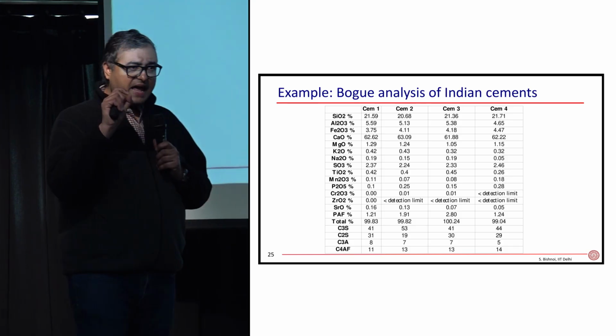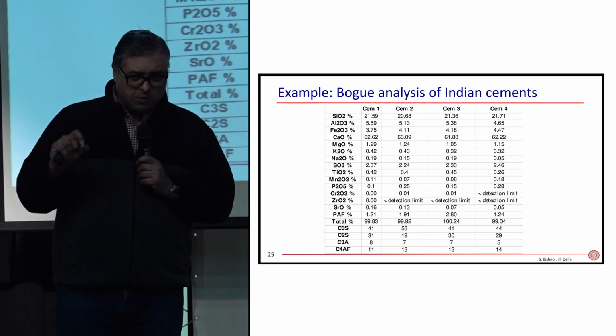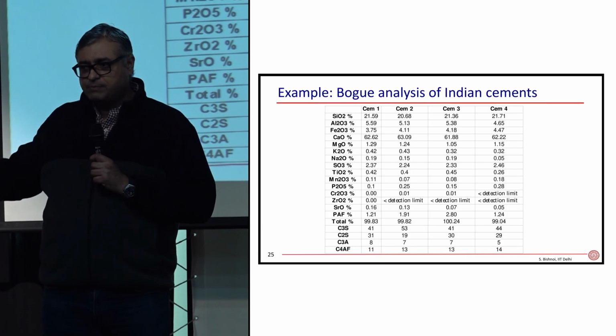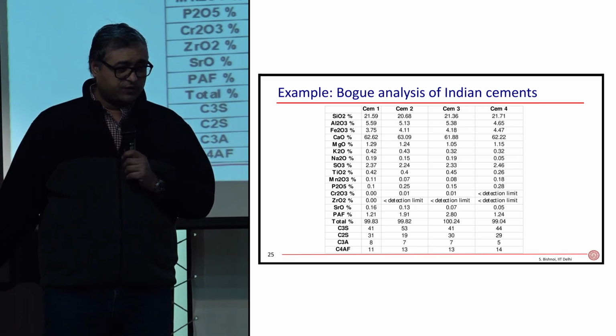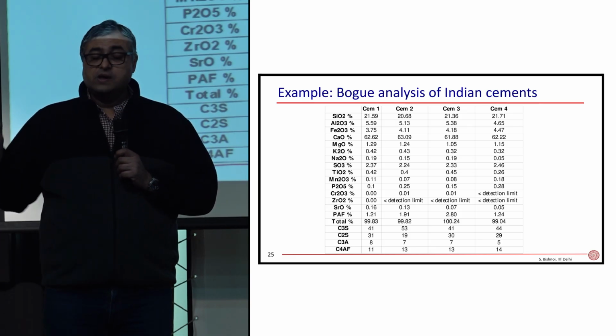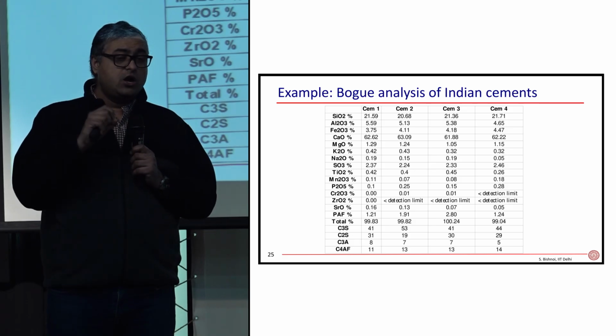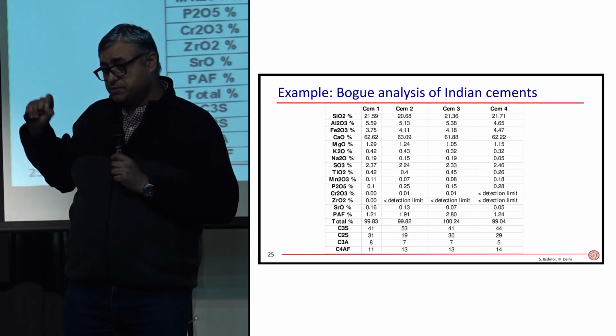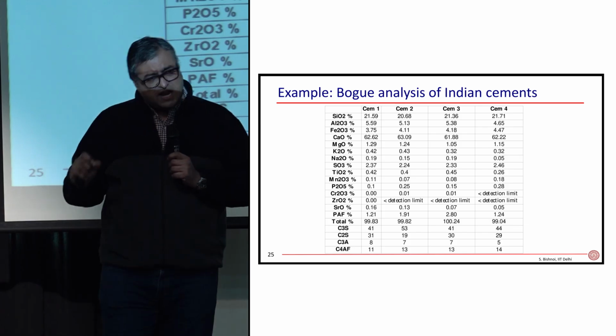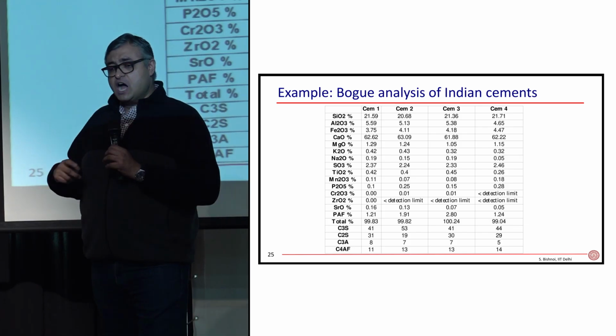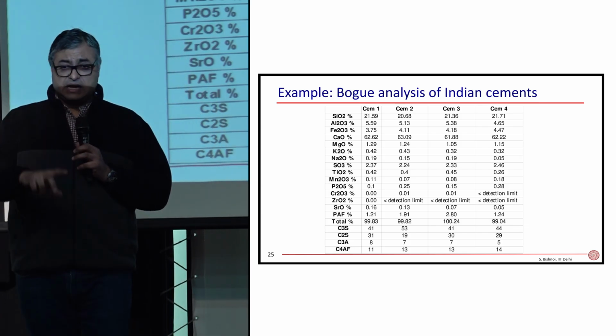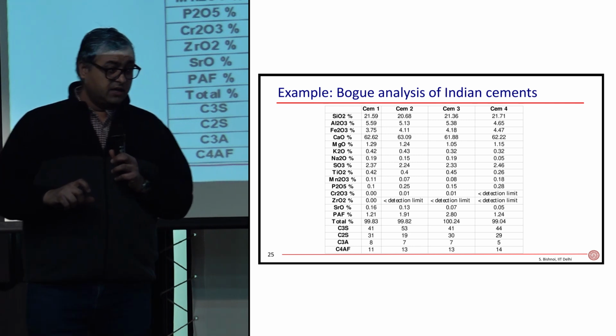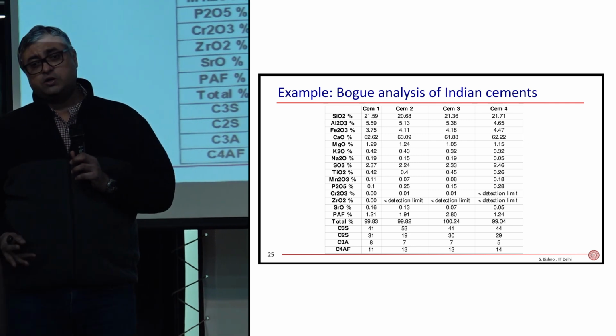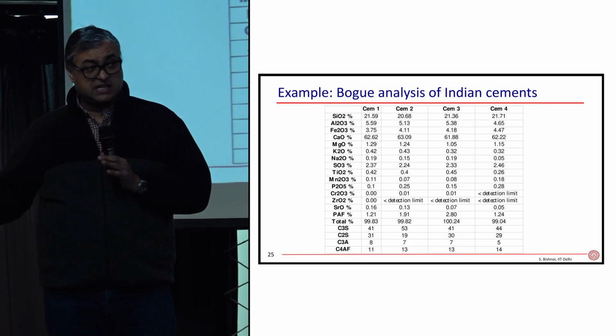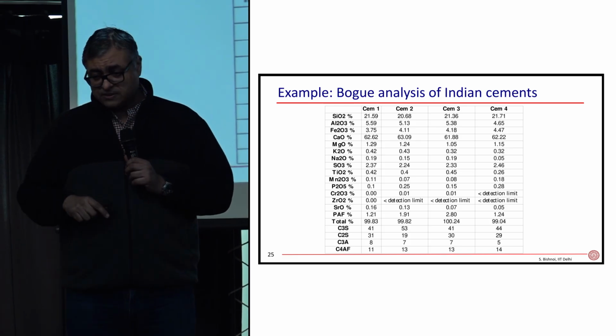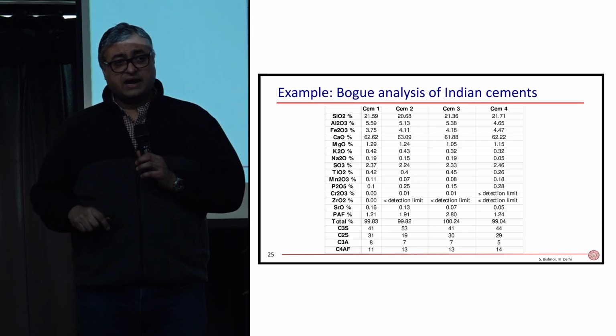So just by an error of 0.5% in your measurement, you can have more than 10% difference in your calculated composition of the cement. That tells you that the Bogue equations are not suitable for finding out the composition of a cement. It's very nice to understand if you've produced a good raw meal that can be put inside your cement plant to produce your clinker, but it is not very suitable to calculate how much alite, belite, whatever is present in your cement for research purposes. For that, you may have to use another method.